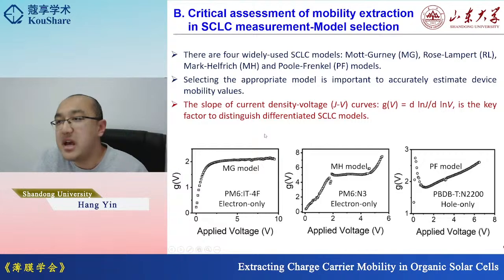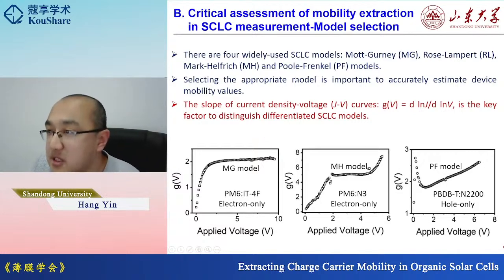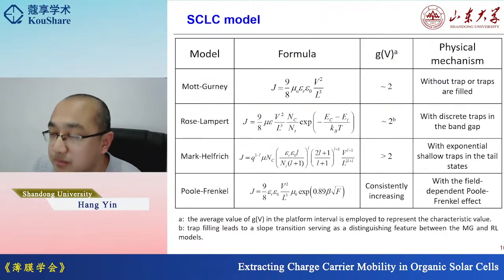And so far, there are 4 types of widely used space charge limited current models. They are named the MG model, the Rose model, the MH model, as well as the PF model. And here, the slope of the current density as a function of the voltage curve should be the key factor to distinguish the different SCLC models, as selecting the appropriate model is very important to accurately estimate the device mobility values.